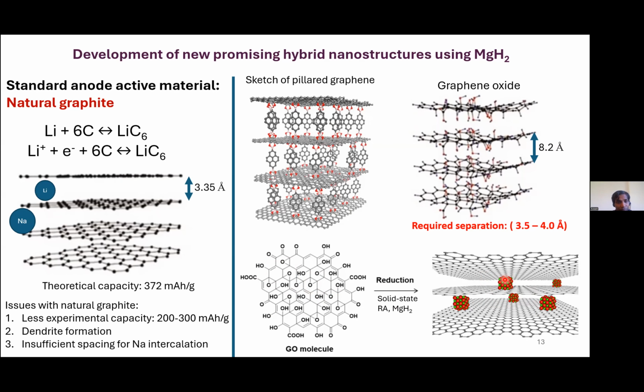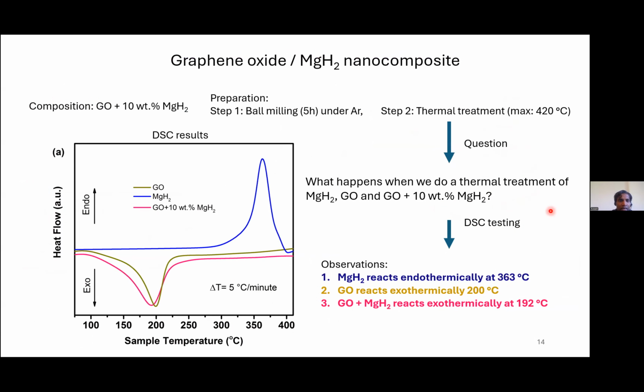And we proceeded in this approach, and what all the things we observed. We made a composition, graphene oxide plus 10 weight percentage MgH2. We also use this type of materials for hydrogen storage, so we know how to play with these compositions. That's how this particular composition was chosen. Firstly, after making this composition, we wanted to test the individual components of it: how magnesium hydride alone would respond to the reaction conditions that we are applying, how graphene oxide would respond, and then the entire composite material altogether.